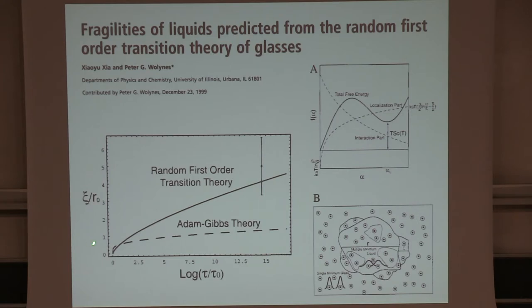When people say Adam Gibbs tells you that you've got growing regions, he used those words, but if you put the numbers into his theory, the size of the regions is about 2 particles at that point. Now, do you want to do a microscopic theory of things that are 8? We're already questioning whether you should do something for something that's 5 by 5 by 5, but I think you'd have even more problems if you did 2 by 2 by 2, and we ask you to extrapolate.